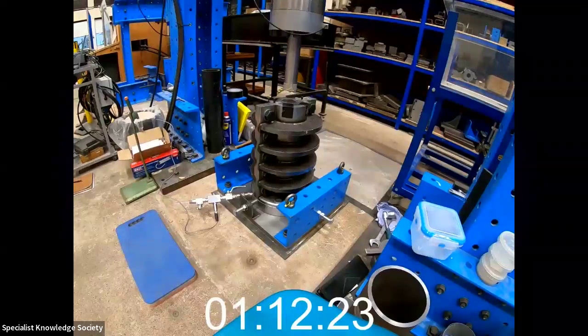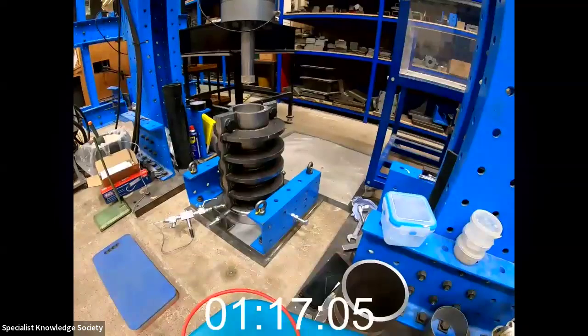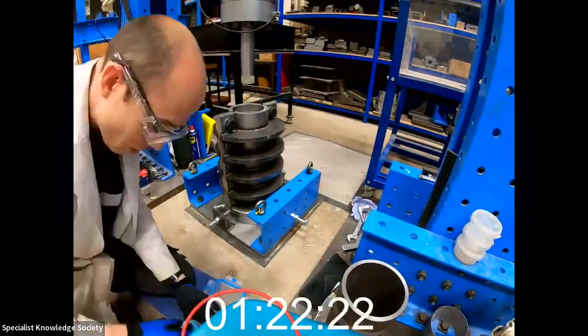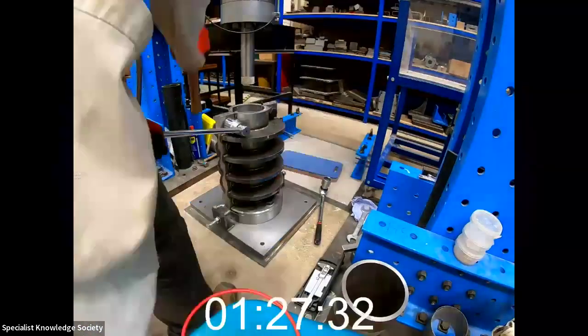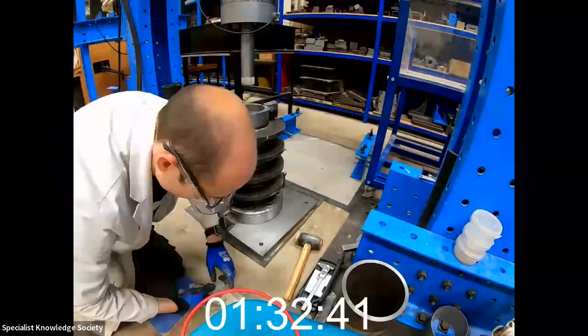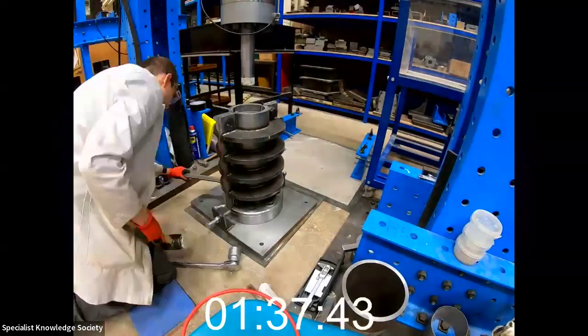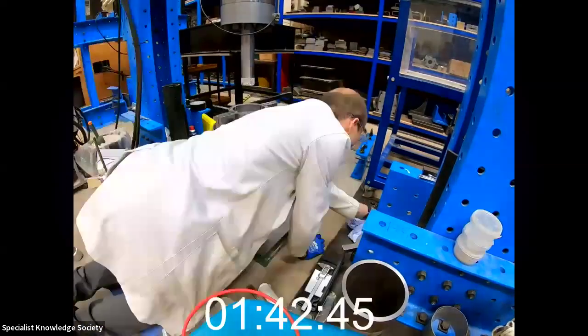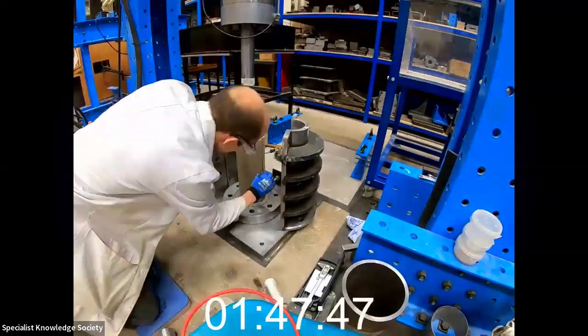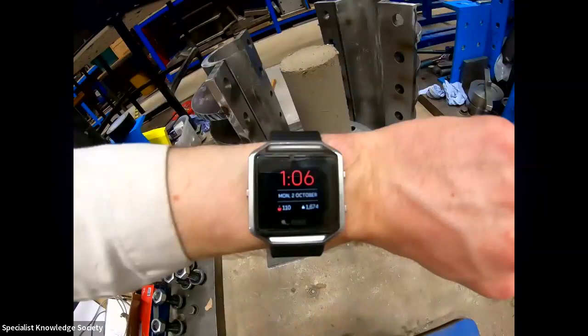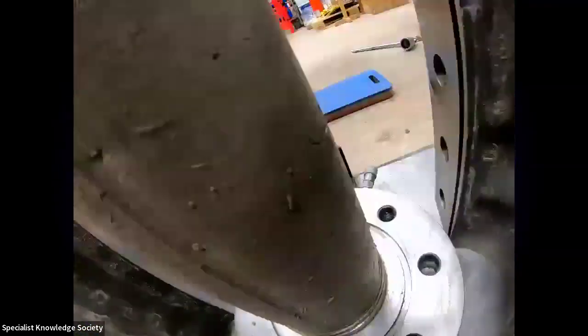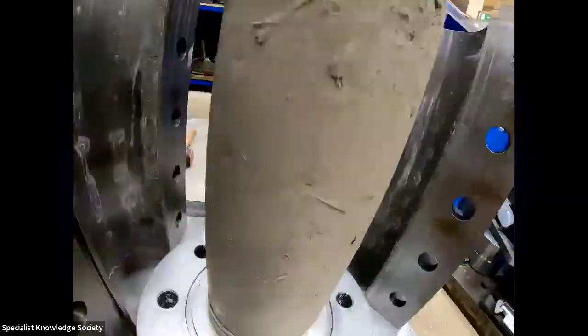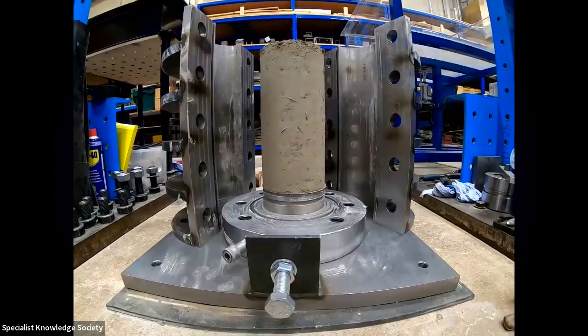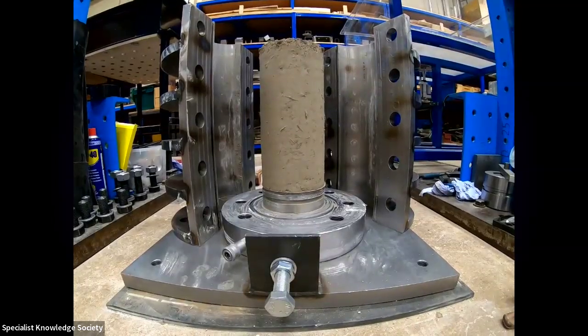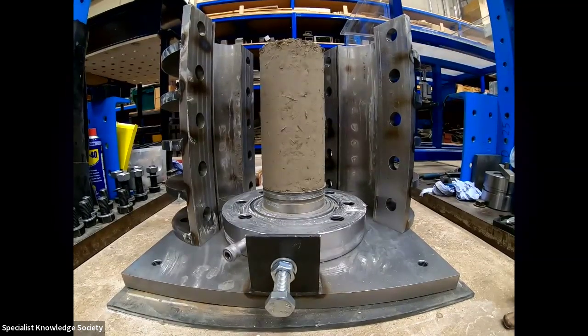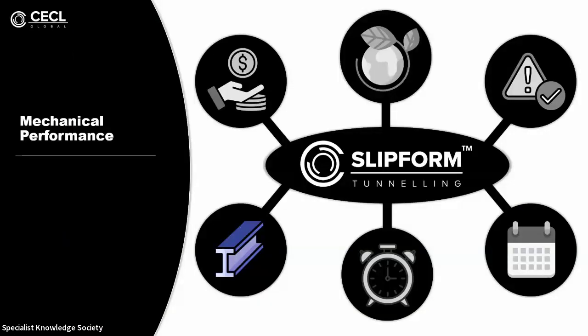This is essentially almost like an oedometer test. What we're doing during the forming process, and I've definitely got a stronger right arm from doing all these bolts up hundreds of times in the lab now. But you'll see when I strip the sample, this is what we're forming very rapidly. So it goes from a flowable concrete through to something with appreciable strength and stiffness instantly because of that high compactive force from the injection pressure.